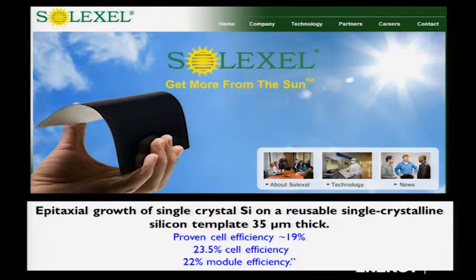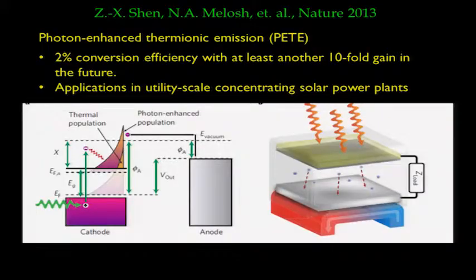There could be other liftoff techniques on a flexible substrate, again, 30, 35 microns thick, for companies like Solexel. And here's one last idea that's being pursued by a couple groups that I know of. This one by Xiaolin Zheng, Nick Melosh, and their collaborators. And it fundamentally goes as follows. In silicon photovoltaic material, you want very high intensity sunlight concentrating, because the higher the intensity of sunlight, the more efficient it gets. However, with higher intensity sunlight, you have a heat loading problem. The hotter it gets, you have all sorts of collisions of the carriers with phonons. So that's bad. So what these guys said is, why not combine the best of both?